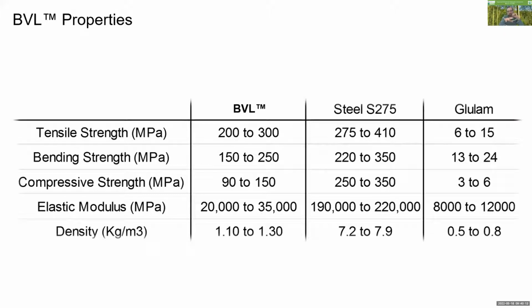So what we did at the end, we also decided to focus on production from Dendrocalamus asper from different parts of Asia. In earlier times, we focused on the Indonesian part, but we said, okay, let's not just focus on Indonesia. Let's produce a BVL with different Dendrocalamus asper from Southeast Asia, and that's the range that we achieved. That shows that even with the lower quality Dendrocalamus asper, in terms of bending strength or flexural strength or MOR, the mechanical properties of the engineered bamboo product that was developed are still much higher than glulam, basically glue laminated timber.